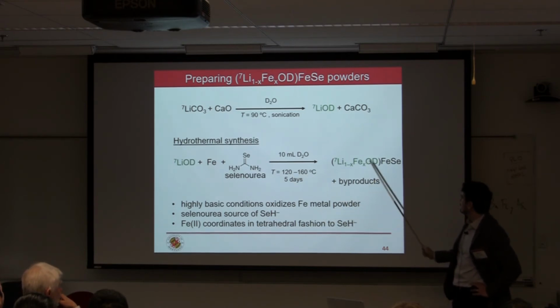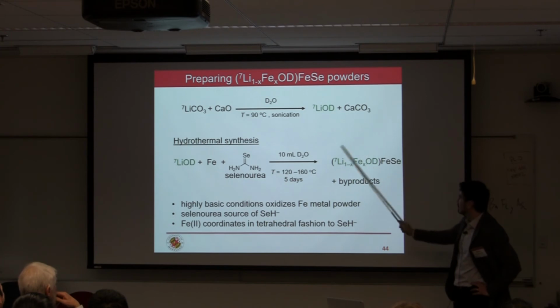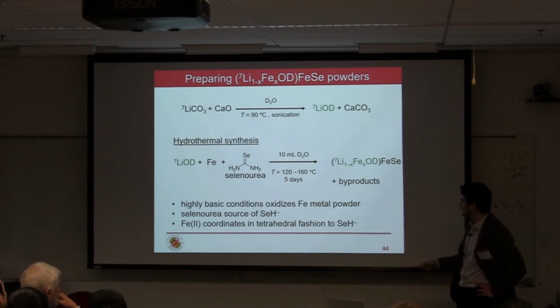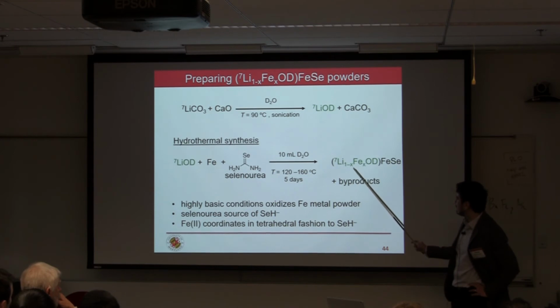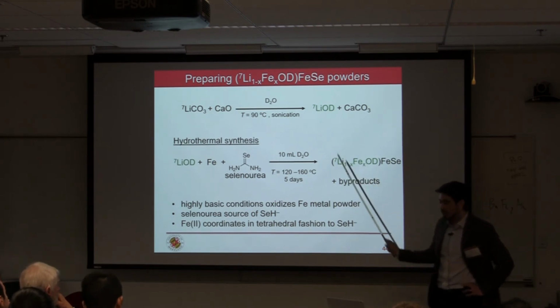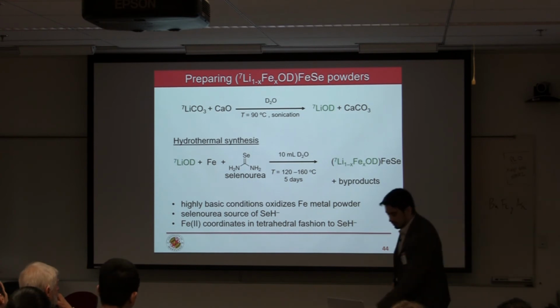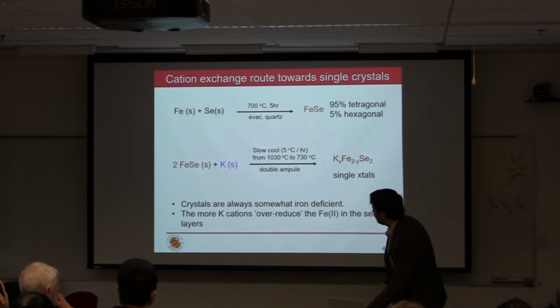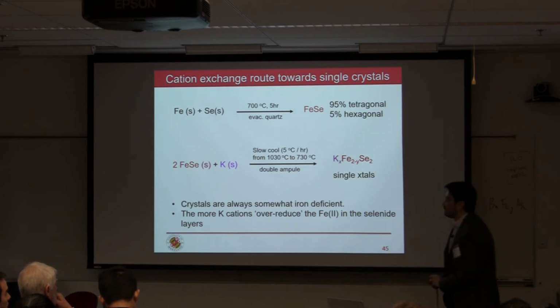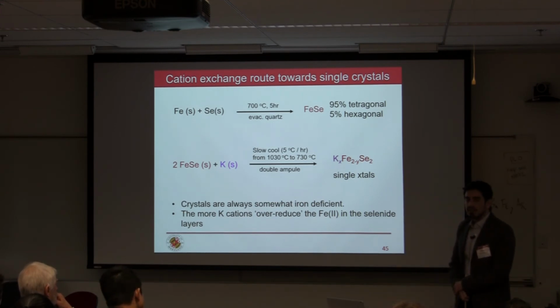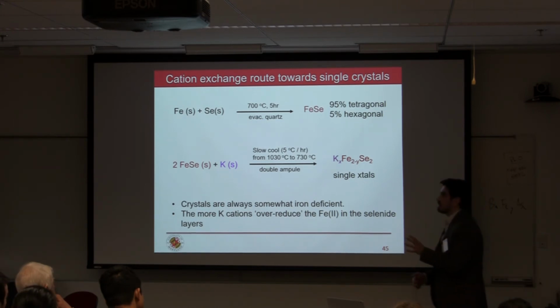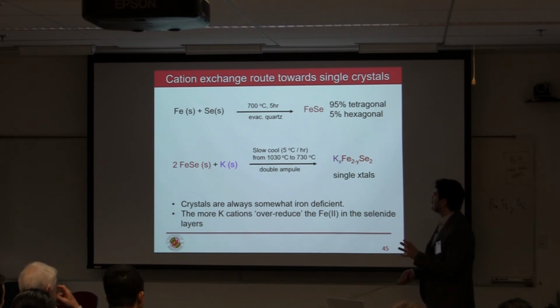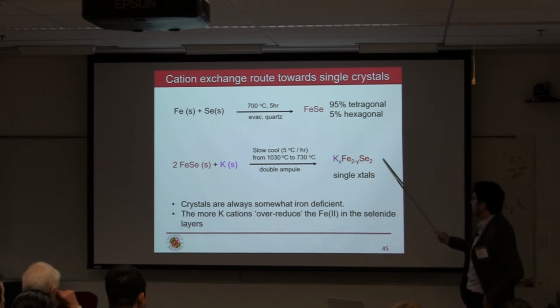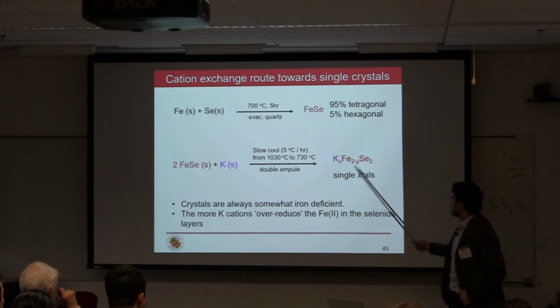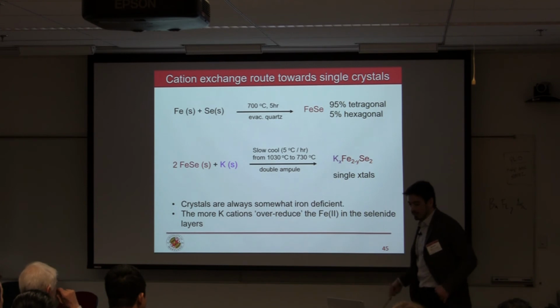Between 120 and 160 degrees C, and you can get nice, this is a polycrystalline mass of lithium hydroxide iron selenide. The crystals that you can grow from these are very small if you use this process here. So sub-millimeter for sure. What we've decided to do to try to grow larger arrays of these lithium hydroxide or deuteroxide iron selenides was to first do a sort of hybrid technique here, where we made, through high temperature techniques, the potassium iron selenide, which already has these layers, and then under hydrothermal conditions convert it to the lithium deuteroxide.